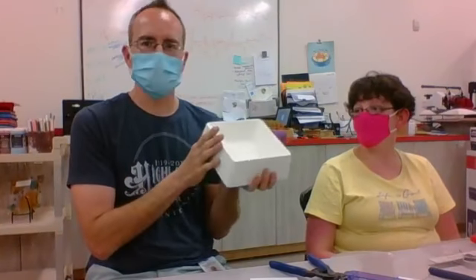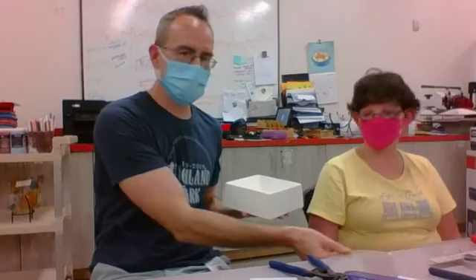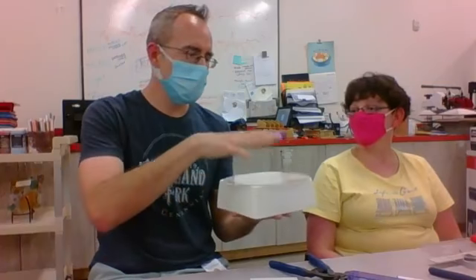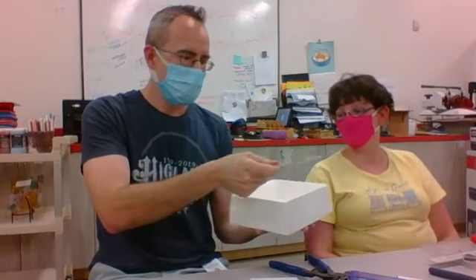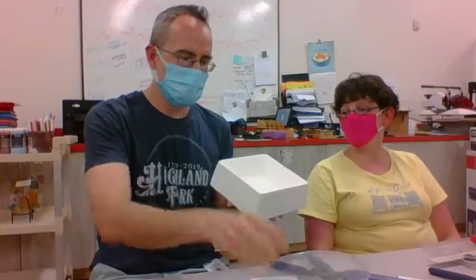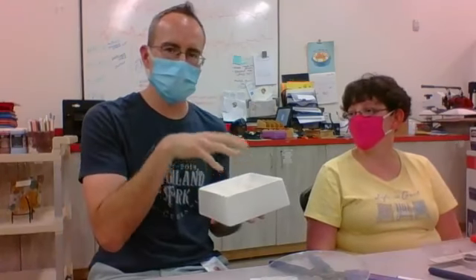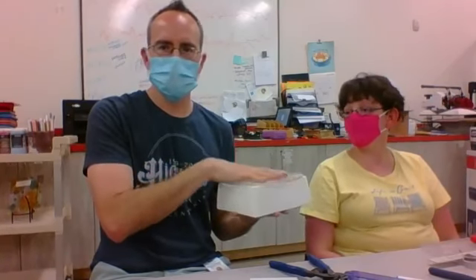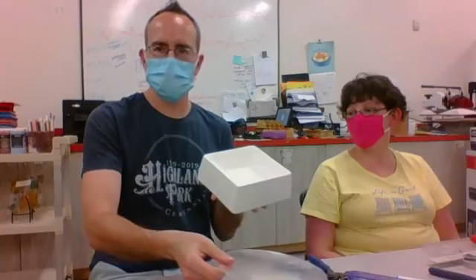So this would be a nice geometric plate. So the glass would sit kind of flush on top. I'm going to steal Morgan's piece of clear here. It's not the right shape at all. No. You'll get the idea. So once the design is created, fused the first time around in the kiln, it sets on this in the kiln, and this has a protective coating on the surface of it. All of our kiln shelves have what's called high fire paper. It keeps the glass, when it liquefies and melts into itself, from sticking to the kiln shelf. It'll come right off. So that glass would sit right on top of the slump mold. We take it up to about 1230 degrees. At that point, the glass anneals to the point where it's just bending. It's not going to melt. It's not going to pull down. It's just going to bend into the shape, and the slump mold's going to catch it and create that shape as well. We've got a couple others to share with you.